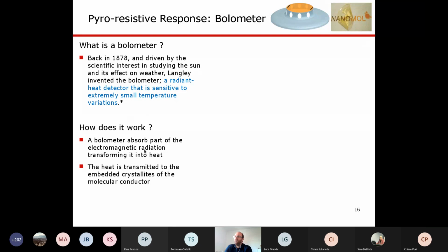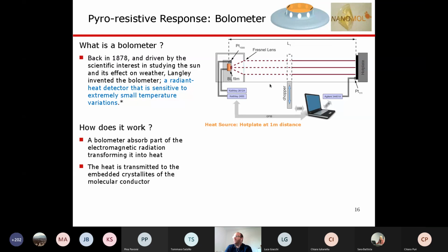And what happens actually is that this radiation heats locally this plastic. This heat is transmitted to the crystals, and the crystals, as I mentioned before, we can measure their resistance. So we made a small setup to try if this complicated explanation actually could work. So we made a hot plate where we can control from a computer its temperature. And then at a 1 meter distance, we mounted one of these films and checked if we can actually see the temperature change of this hot plate.